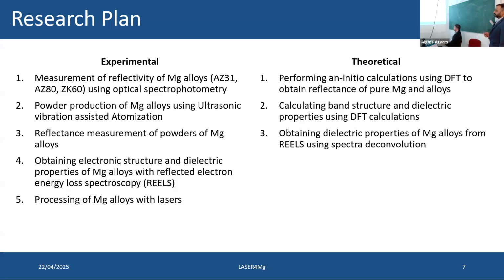Especially the ZK60 is in demand by the space sector because of its higher strength, very close to some space grade aluminum alloys. And so the reflectivity was measured for these alloys. I also turned these alloys into powder, which I will not talk too much about here. And the dielectric properties were measured by REELS analysis.